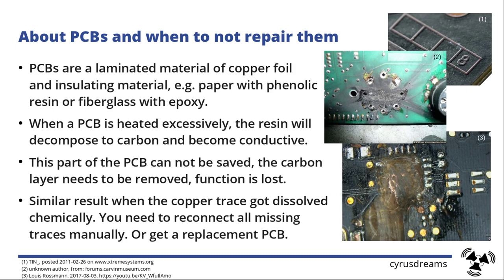And you might even have that in a lower layer. So you have to identify, if you have a multi-layer board, you can look out for those fiducials like this. This one is then an 8-layer board. And in this window, if you put that against the light source, you might see the 7 in there, 6, 5, and then there's another one which counts down to 1. If you want to salvage the PCB, you cannot salvage the function on that point.